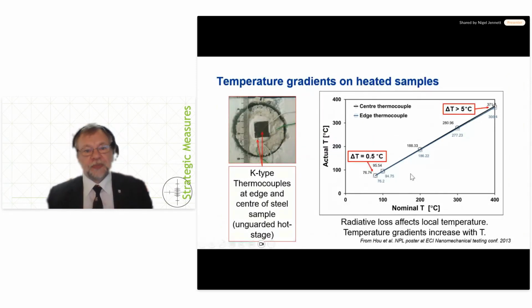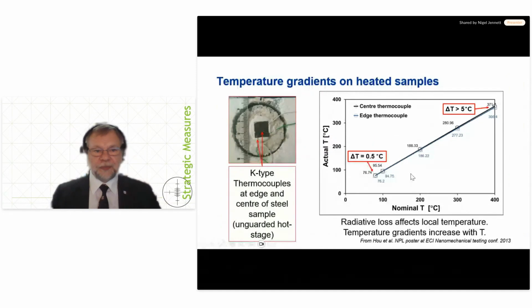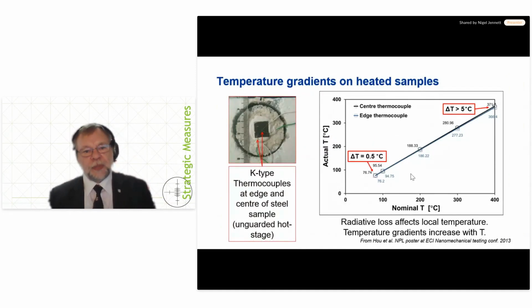So how do you measure it? Well, stick a thermocouple on it, obvious, right? So if you put a thermocouple in the middle of a sample and a thermocouple at the edge of the sample, would you get the same reading? The answer to that is no. And that's because you get radiative losses. So heat radiates away from a hot thing, called black body radiation, and the edges lose heat and get supplied from the center. So the center tends to be hotter than the edges.